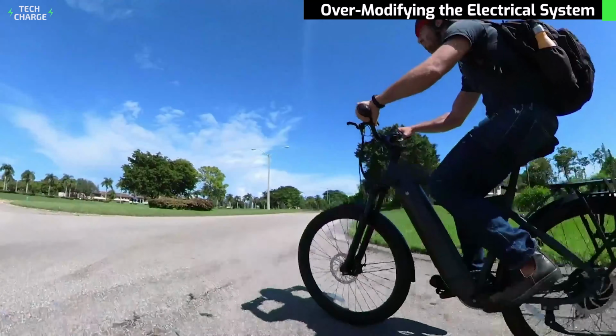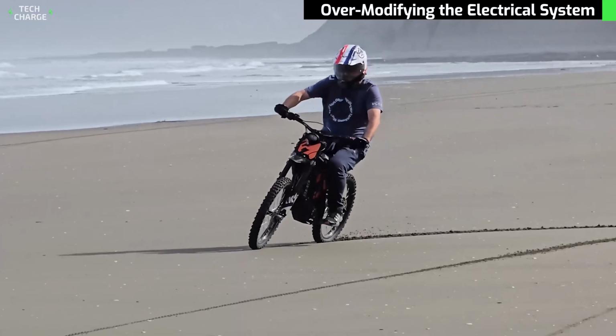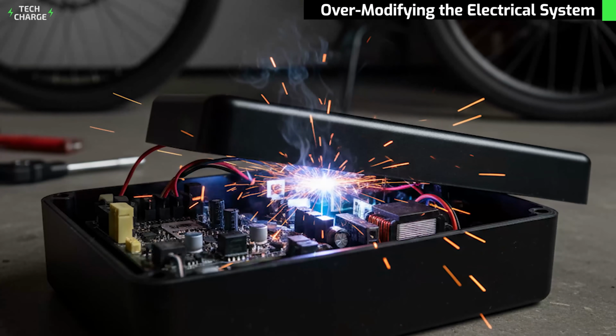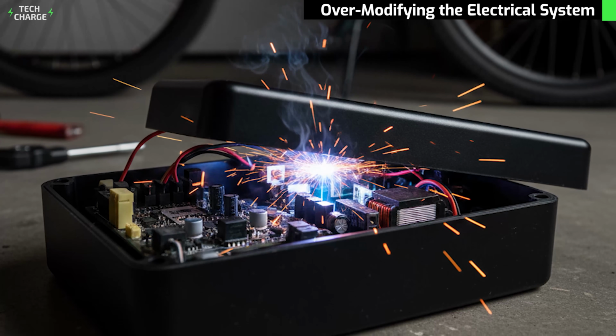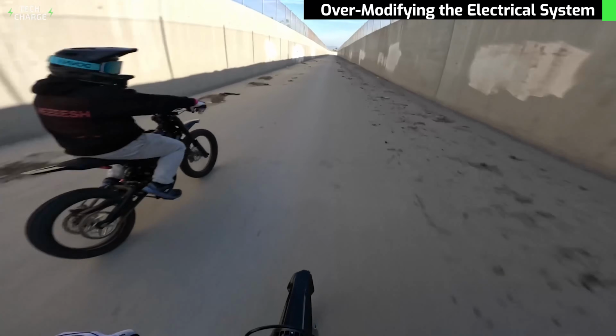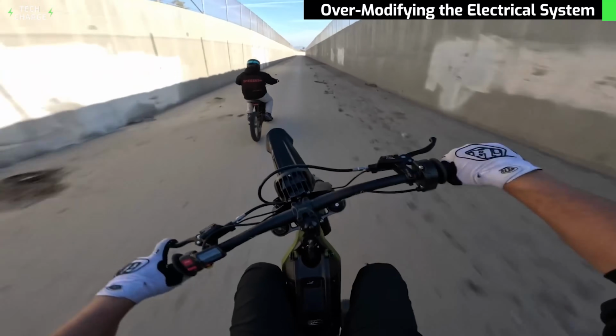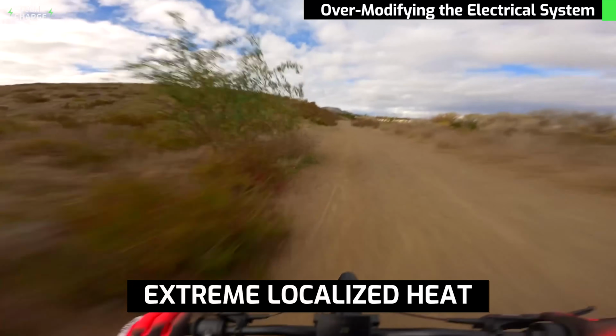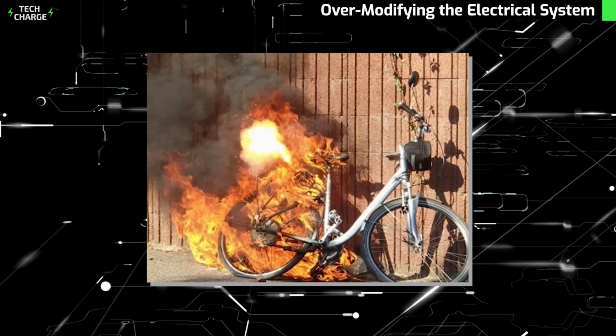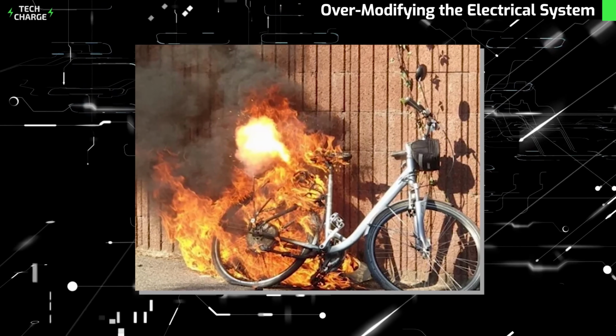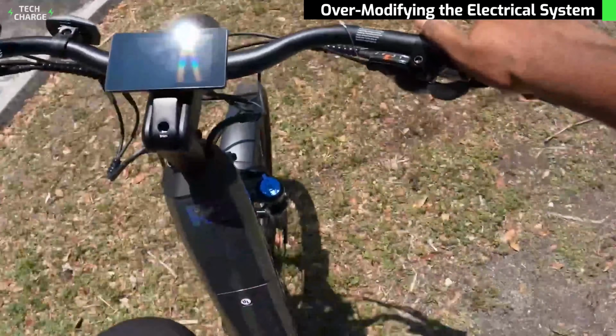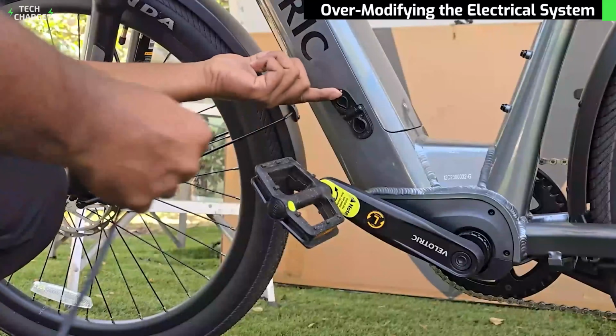The excess voltage can arc across circuit board traces, melt solder joints, and cause sparking inside the controller housing. This isn't a slow degradation process. It's sudden component failure that generates extreme localized heat. That heat can ignite nearby materials or trigger thermal runaway in the battery if the failed controller creates an electrical short that feeds back into the battery pack.